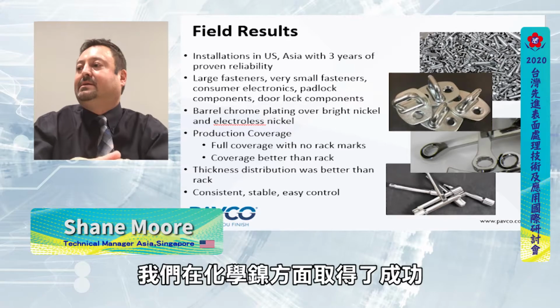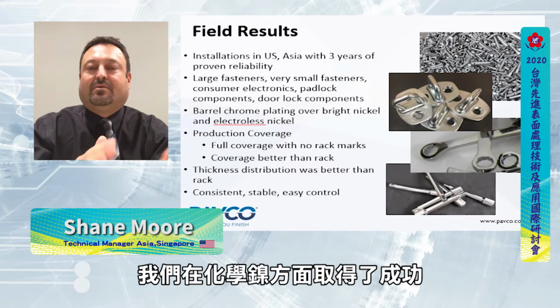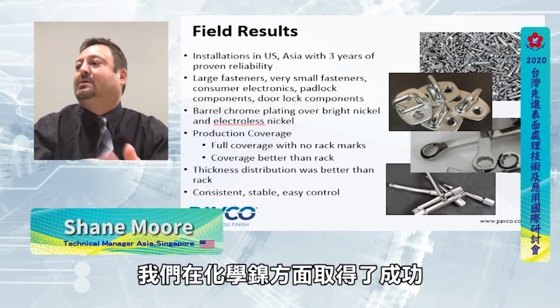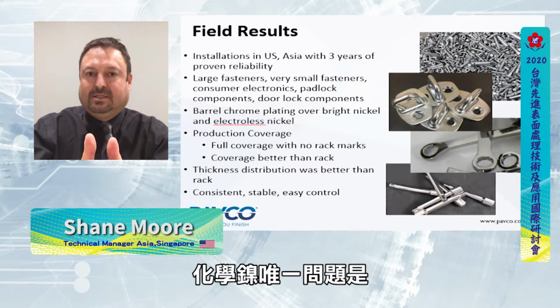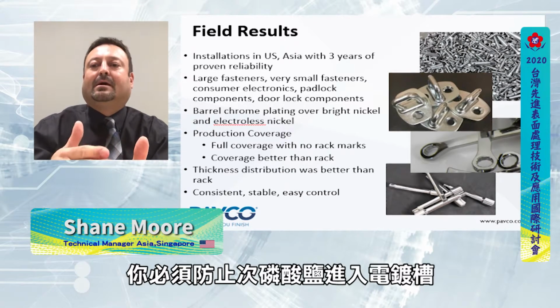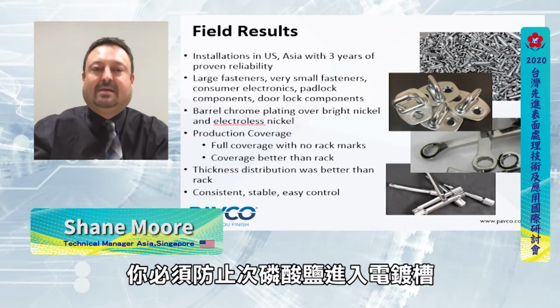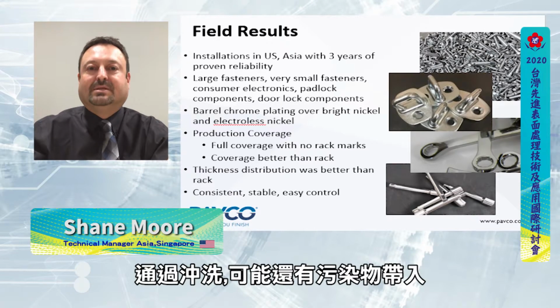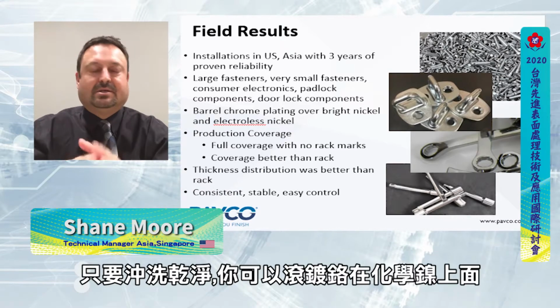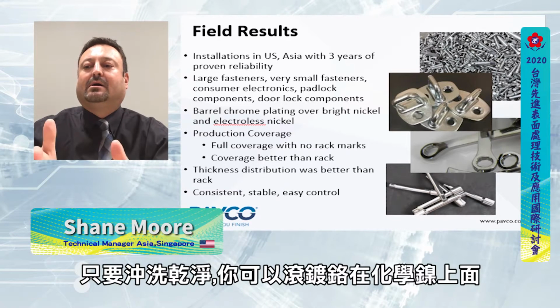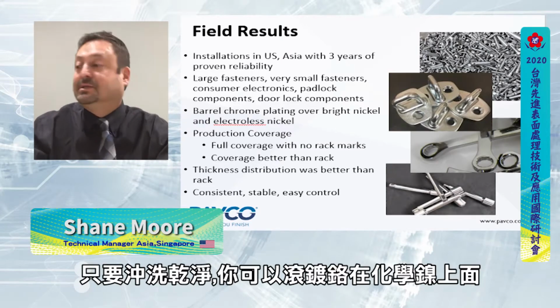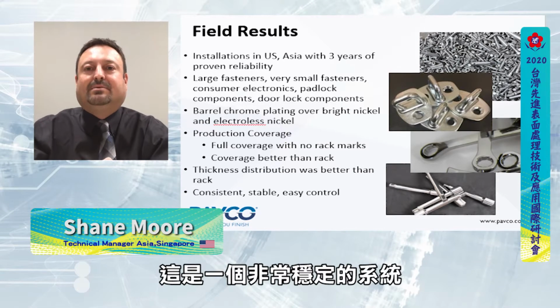We have been successful with plating over electroless nickel. The only thing with the electroless nickel is that you have to prevent the hypophosphite from getting into the tank through the rinsing, because it seems to be a contaminant. But as long as the rinsing is good, you can plate the barrel chrome over electroless nickel as well. So it's a very stable system.